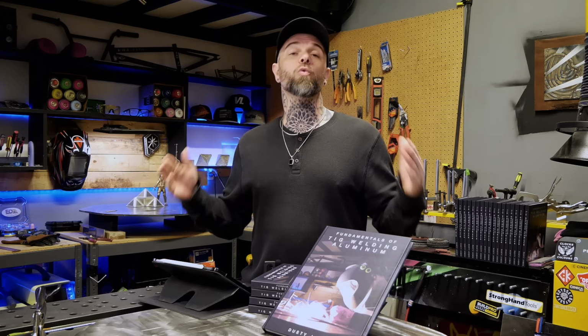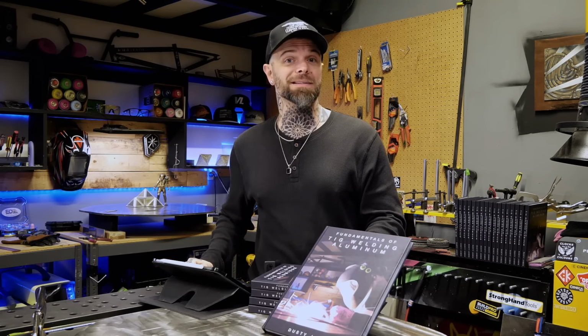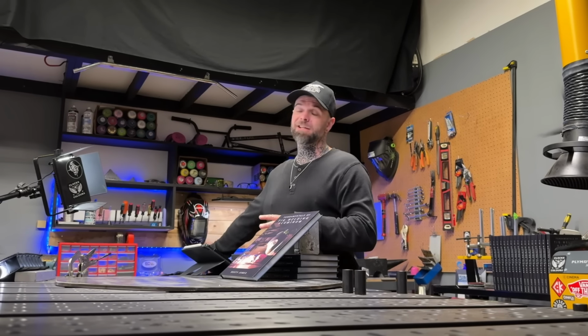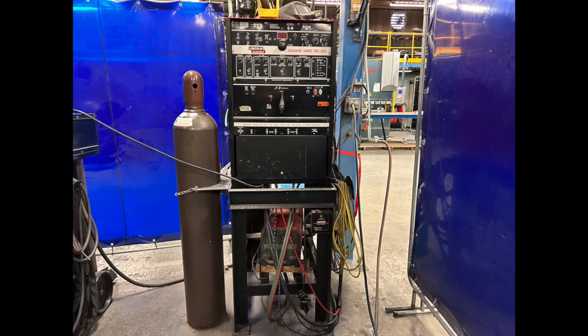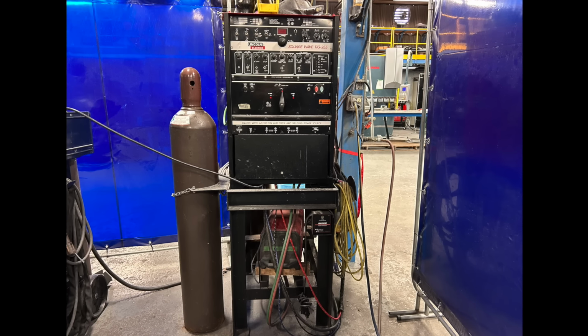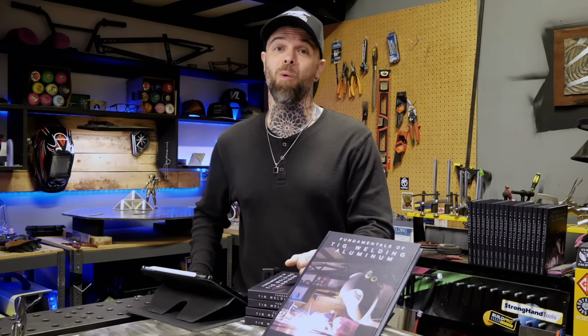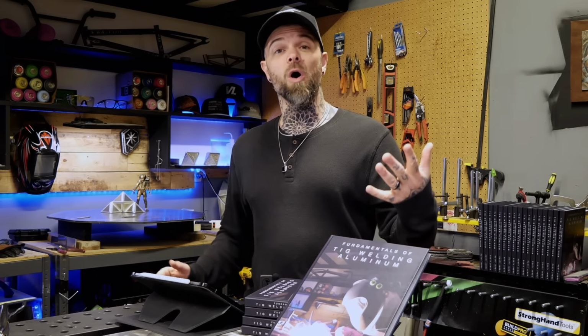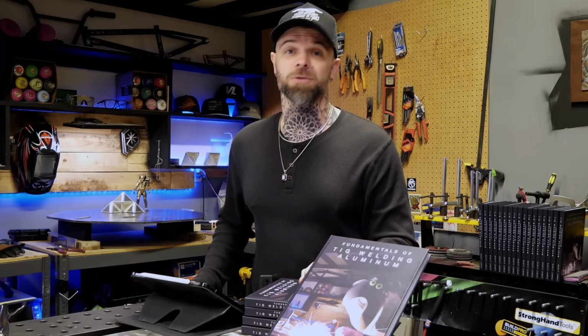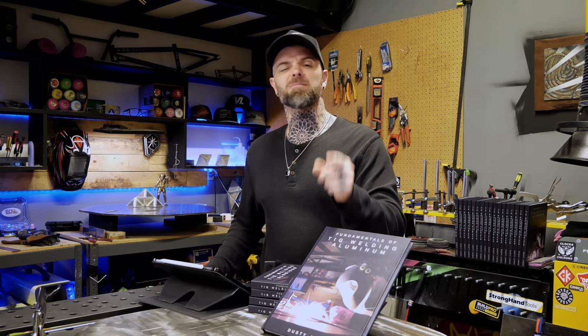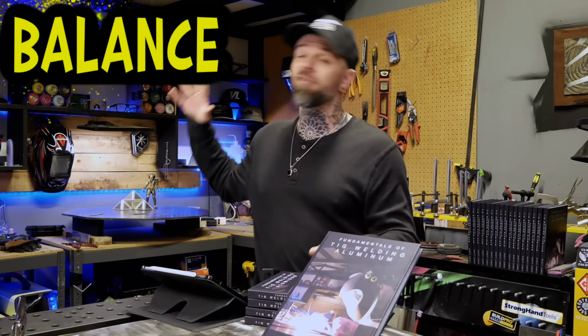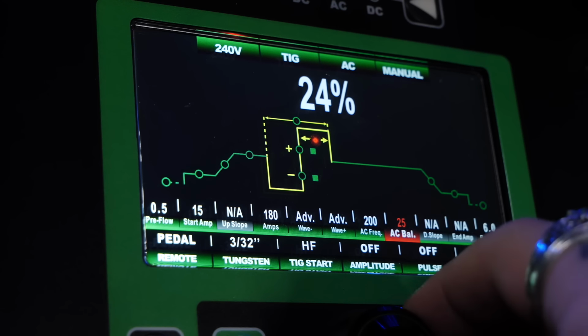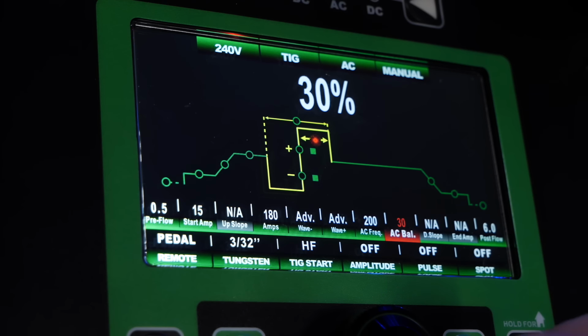Hear me out. I have done over 20 years of professional TIG welding experience, combined with certification, using all kinds of fancy gear, the fanciest stuff that you can find these days. And I've also done some work with some old school type machines that I love. So after experimenting with everything, why don't I use a pointed tungsten? Because every weld that we will all do is going to be different from one another for the most part. The one most important setting that keeps your tungsten perfectly pointed is the precarious setting of balance. This will balance the different polarities between DC positive and DC negative, and anytime we start to increase the positive side, we can potentially start to see the tip of the electrode become misshapen or deformed. Sometimes you can see it flutter a little bit, wobble around slightly.